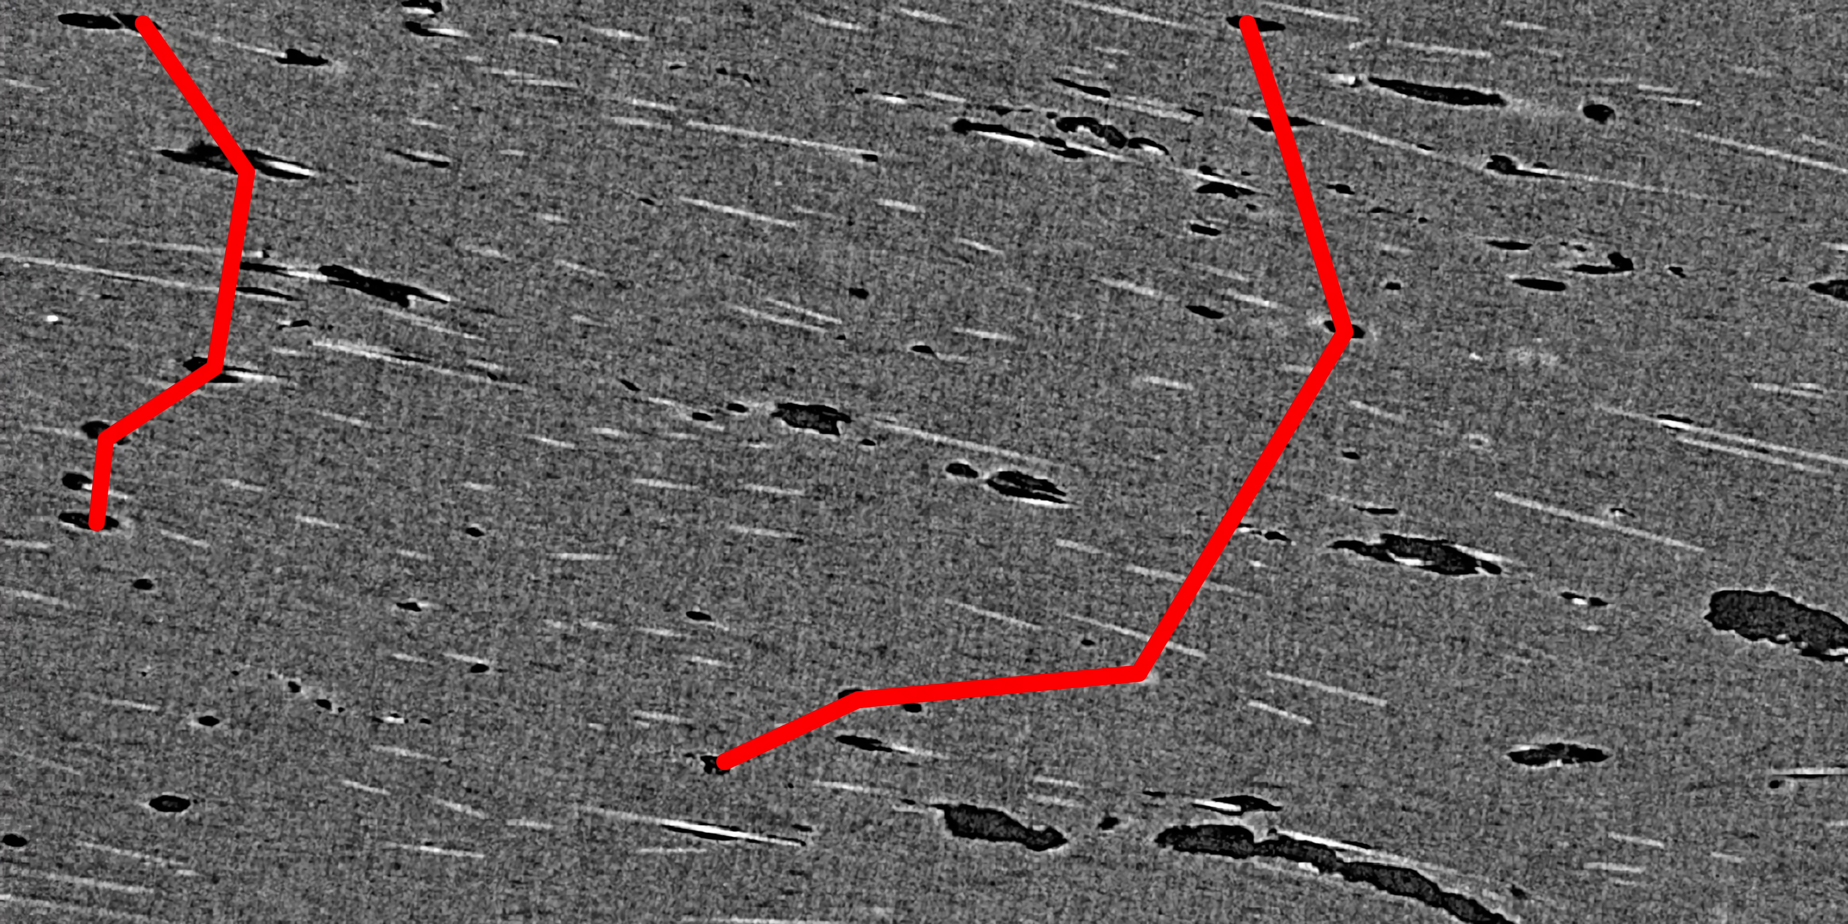So that would be fine. I mean, if you press on it, the fiber would still get some forces, or it would prevent it from bending or whatever. But those voids are not just air bubbles; they are actually stress concentrations. You have to see if a void is angled at 90 degrees, which the end of the carbon fiber actually is. You have a sharp angle there where a crack can start, and it can propagate from one void to the next void to the next carbon fiber void, and actually weaken your part.